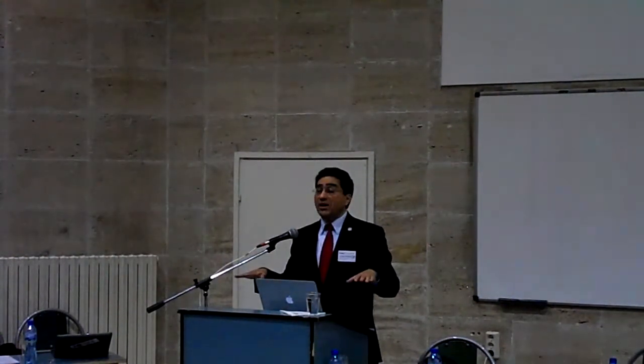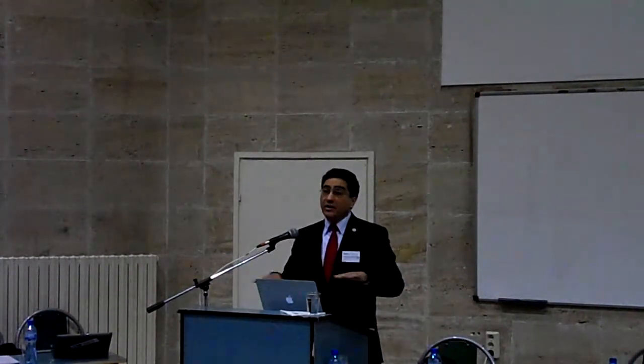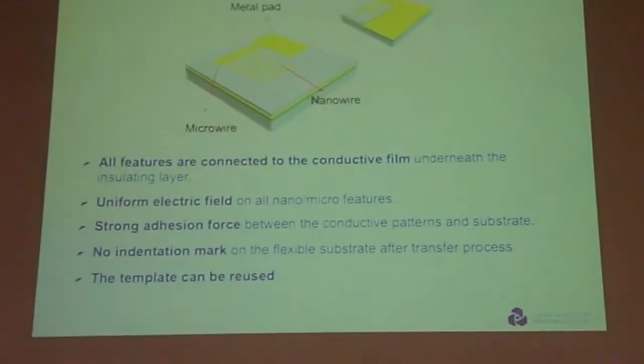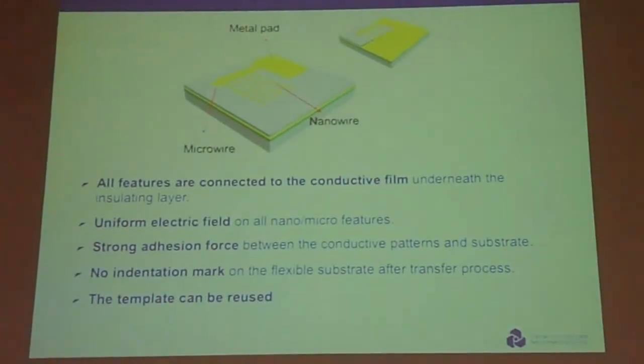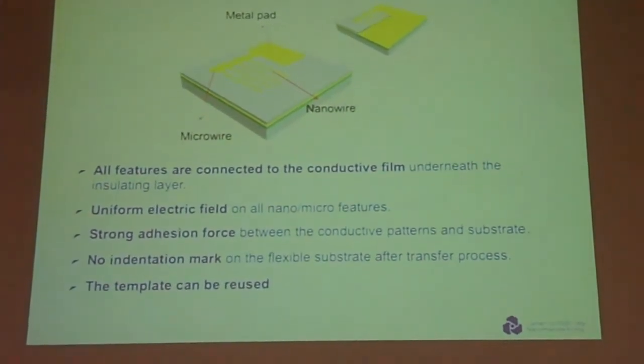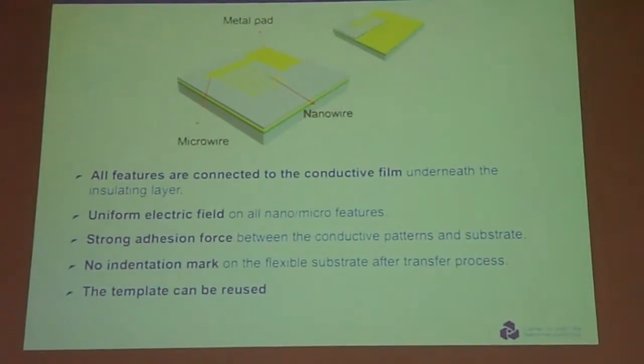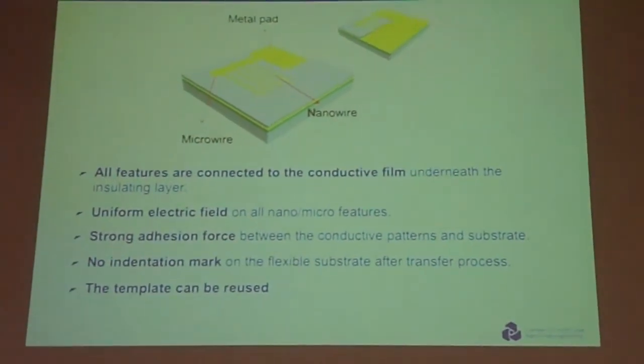And what this means is that we have all the wires, the nanoscale wires, the microscale wires, and the macroscale wires, all connected underneath with the film. So you can see here they're all connected with the film underneath, and that will give each wire, whether it's nano, micro, or macro, the same voltage, and that means the same electrostatic force to attract the particles, and it makes it very strong. So you will not damage the wires, and it also makes it very flat so that you can print very easily. And this technology that we use is not new actually.